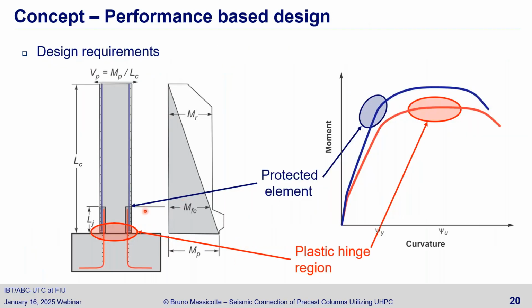So, to follow the usual way of doing seismic design, you make sure that your ductile elements, the reinforcement at the bottom here that is in the footing, yield, and you get the ductility from that reinforcement. And for the part of the column above the joint, above where the plastic hinge region would be located here, those elements are protected. So for the same load level, you will remain nearly in the elastic regime, which would allow you to do whatever you want for that element.